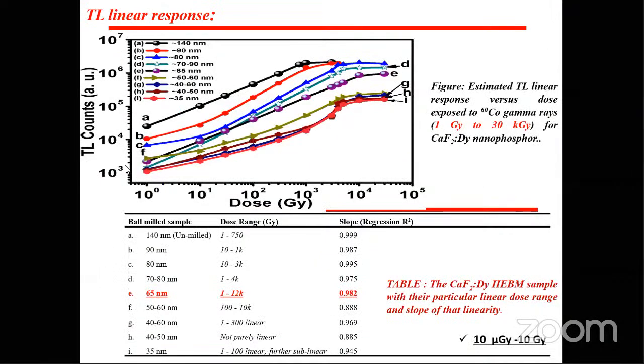So this is the dose range response, and finally we achieved that the 65 nanometer particle size sample shows a range of 1 gray to 12 kilogray, having a slope of around 0.982. Okay, that is the slope of that particular dose response.